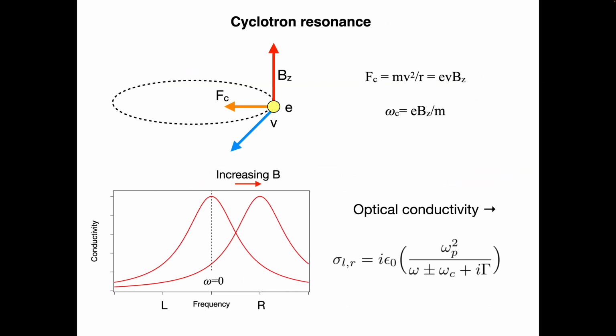Now, one thing that we're spending a lot of time on now is kind of related in a sense, but also not, where we're applying very large magnetic fields to material systems. And again, looking at the Drude response, but seeing how the Drude response changes when you apply magnetic field. I mentioned this yesterday. If I have the conductivity of a system, and I imagine that its response is given by this kind of Drude-esque response, if I do a DC experiment, I only measure the zero frequency value of this quantity. When I'm doing my AC experiments, I learn this whole shape here, its width, this area. I get a lot more information when I measure the whole spectrum. I'm not just picking off the DC value.